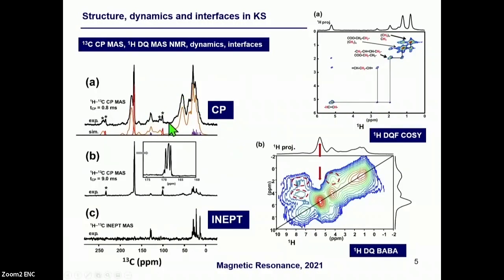So here you have the classical and the standard carbon-13 NMR spectra related to a kidney stone. And you can see that it's a complex spectrum, but you can completely edit it by playing with the contact time. And you can, for certain contact time, overestimate the protein part. And you can also, by playing again with the contact time, overestimate the inorganic part corresponding here to the calcium oxalate in its monohydrate phase.